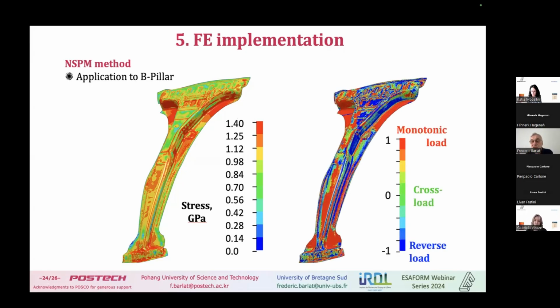But anyway, we're able to finish the simulation. And here, what we can do is look at whether the material experienced some strain path change. For instance, red is monotonic loading. When we have some blue, it's because we had reverse loading. And if you have some green, it's because not far before the end of the simulation, we had some cross-loading.